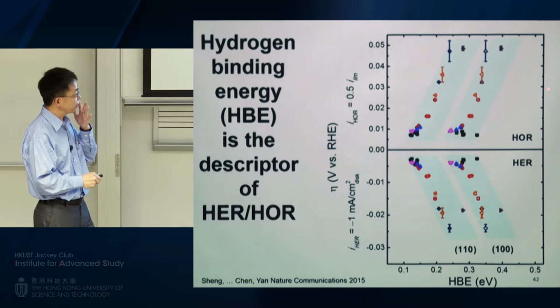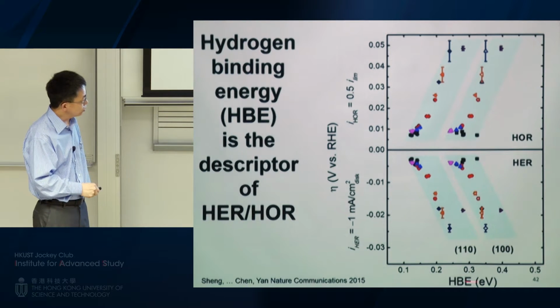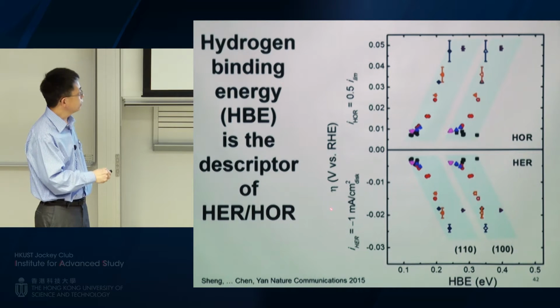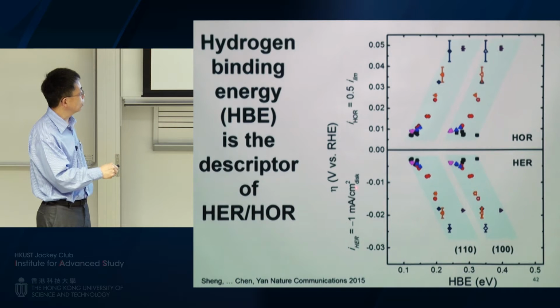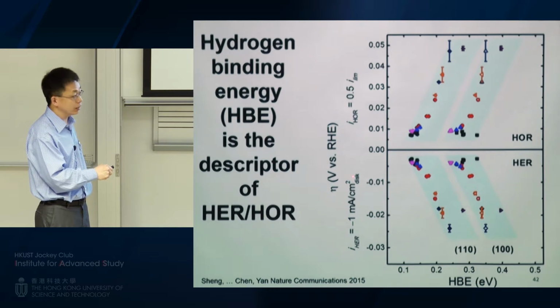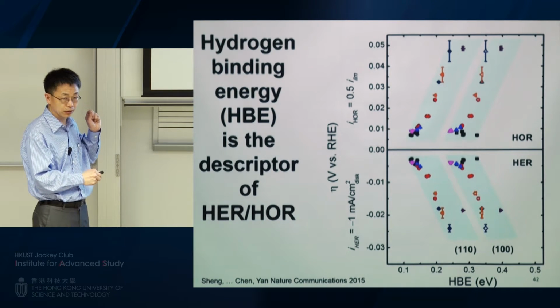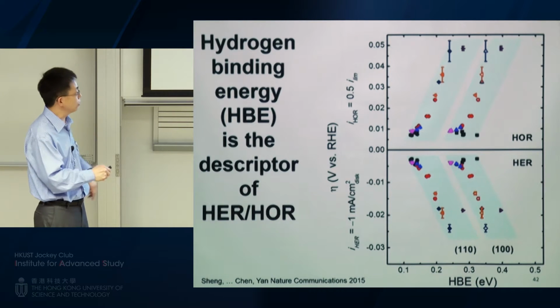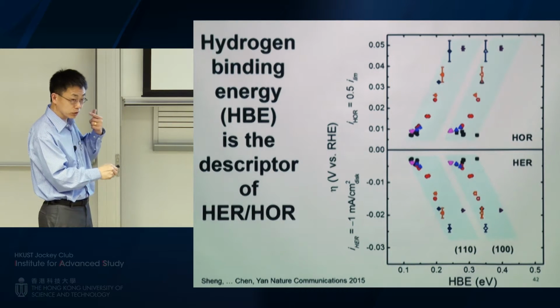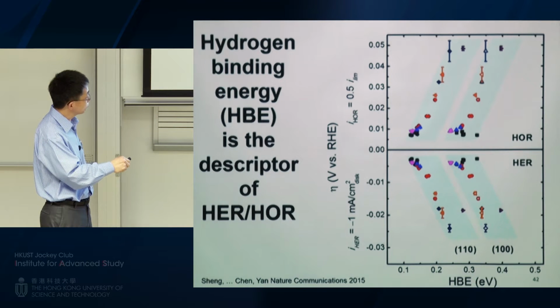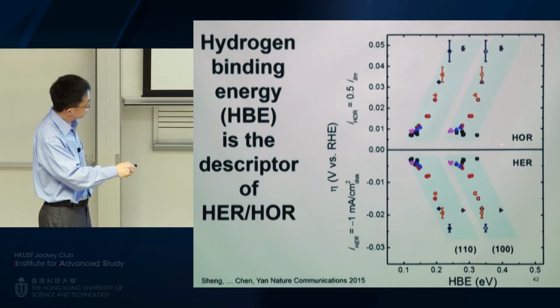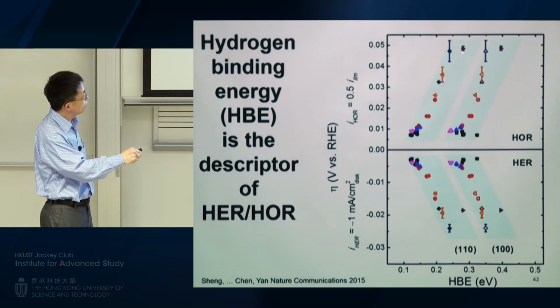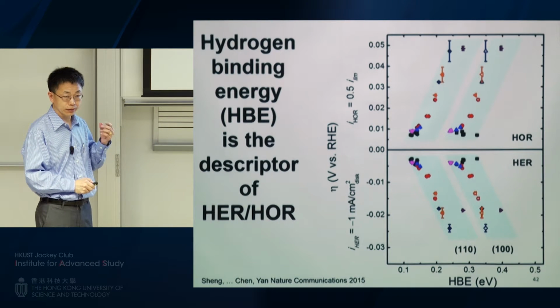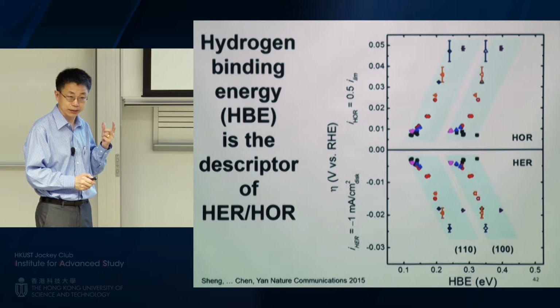So now I'm going to show you the correlation. So the horizontal axis here is hydrogen binding energy going higher and higher. And this is the overpotential of either HOR or HER. So overpotential meaning if you have higher overpotential, the reaction rate is slower. So let's focus on HOR, which is of more importance to me. As the binding energy goes higher and higher, you see the overpotential is getting higher and higher. So indeed, this is what we expected, right?